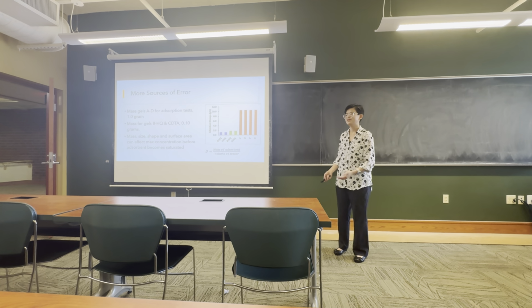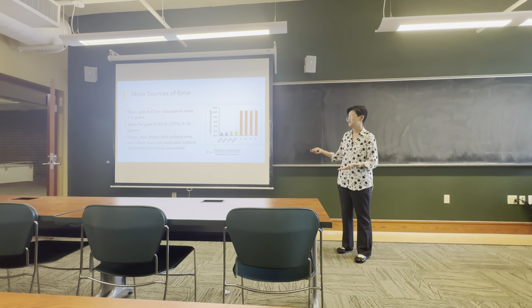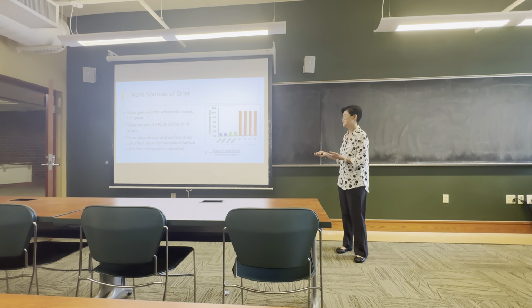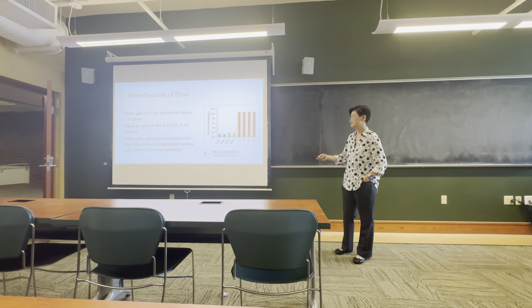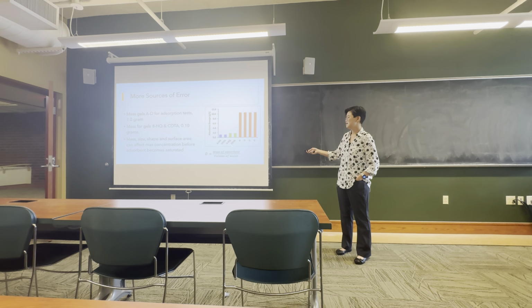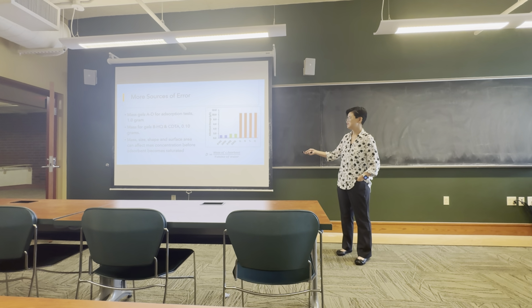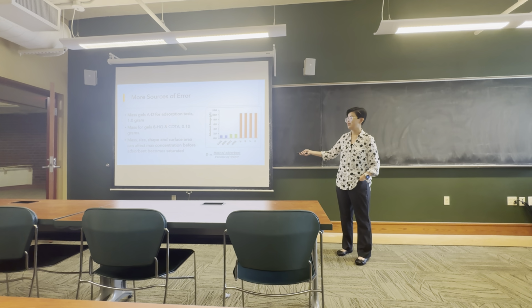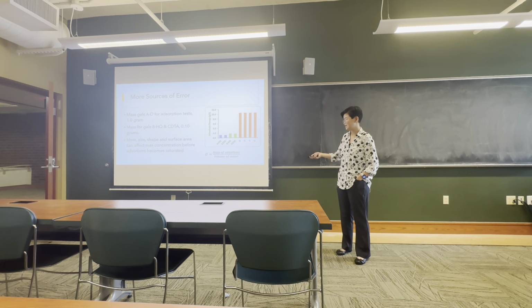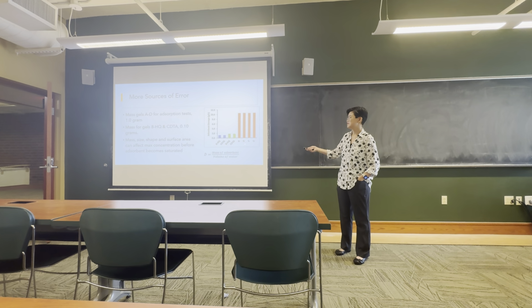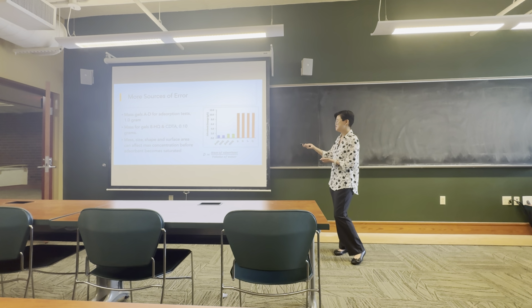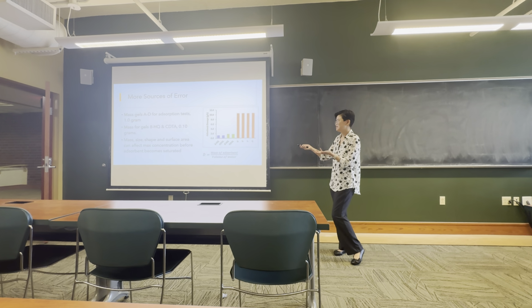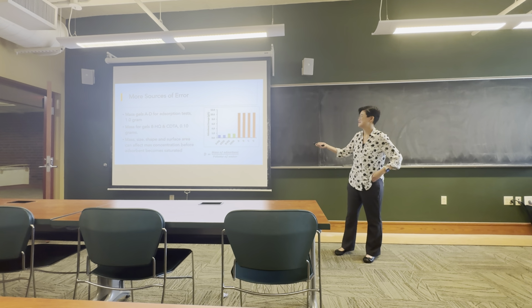The amount of the adsorbent you use is important because it affects the surface area, it affects the amount of binding sites available, and it affects the maximum concentration before your adsorbent becomes saturated. And so you can see this is the adsorbent dosage here. So this is the mass of adsorbent per volume. I used 100 milliliters for all of my tests. And you can see how different this is. So it really wouldn't be fair for me to make any conclusions about which one's better because I didn't even use the right amounts of the gel, so, okay.